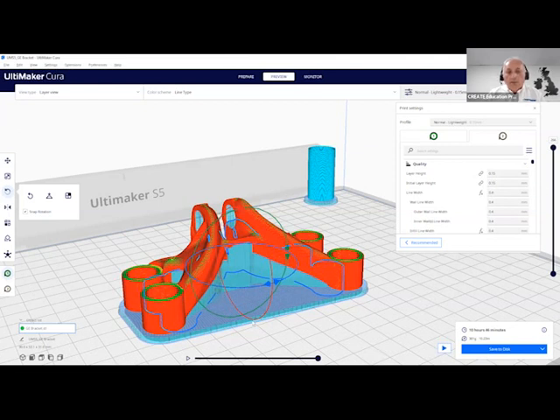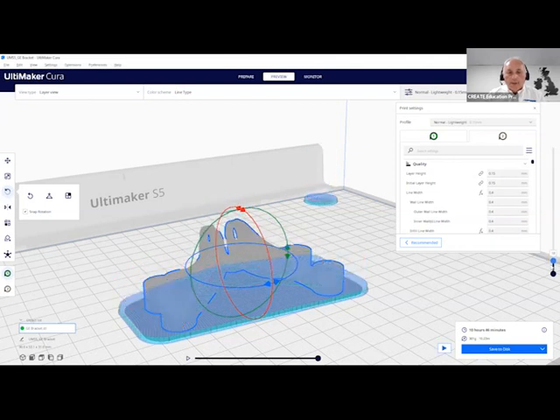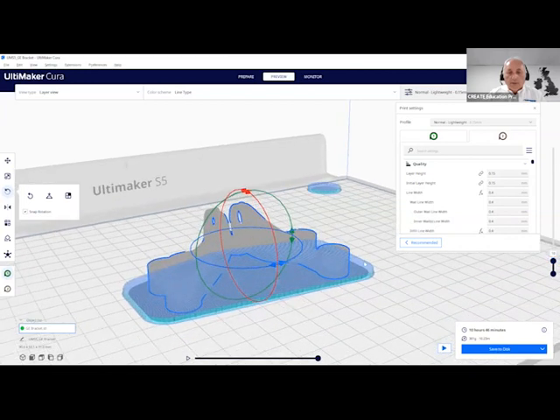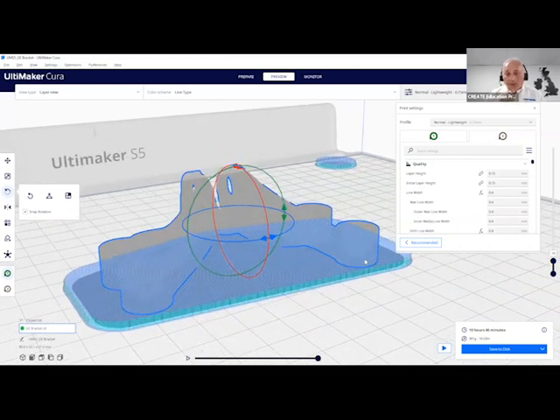You'll notice that this part is actually sat on a plate, and this is what's called a shrinkage plate. So if I go down to the bottom of this part, first of all, it prints about 3 millimeters thickness, not completely dense. It tries to optimize material usage by not making this a completely dense plate, but it prints a 3 mil thick plate in the same metal material as the model. When it gets to that 3 millimeters height, it lays down a single layer of the white ceramic material. And once that's laid down, it starts to print your model.